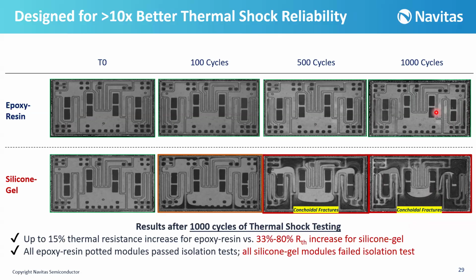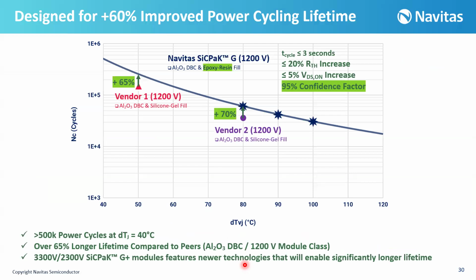So we can say that there is up to 15% thermal resistance increase for epoxy resin, but in silicone gel, we have a 33% to 80% increase in thermal resistance. And all epoxy resin potted modules passed the isolation test, but all silicone gel modules failed the isolation tests. And here is a comparison of power cycling lifetime between these two types of modules, with epoxy resin and silicone gel. As you can see, we have more than 65% higher power cycling lifetime compared to one vendor and more than 70% compared to another vendor. It shows over 65% longer lifetime compared to the silicone gel, as I mentioned.